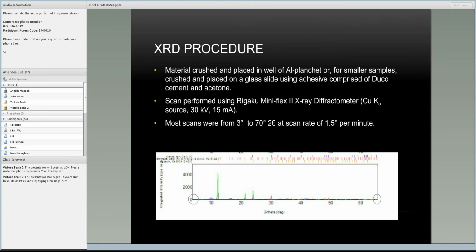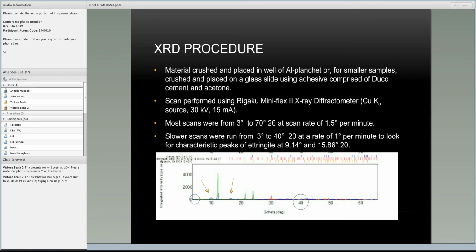Most scans are run from 3 to 70 degrees 2 theta at a 1.5 degree per minute scan rate. Slower scans, especially if we're looking for ettringite, run from 3 to 40 degrees 2 theta at a rate of 1 degree per minute. The ettringite peaks are characteristic at 9.14 degrees and 15.86 degrees, and that's what the little yellow arrows at the bottom are pointing out, the 9 and the 15 degrees for ettringite.